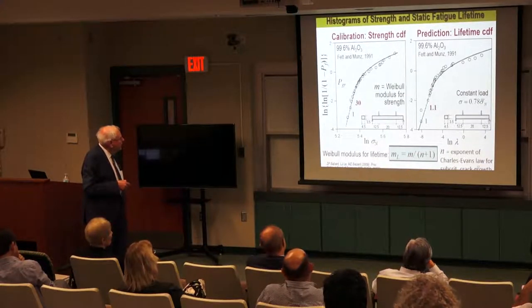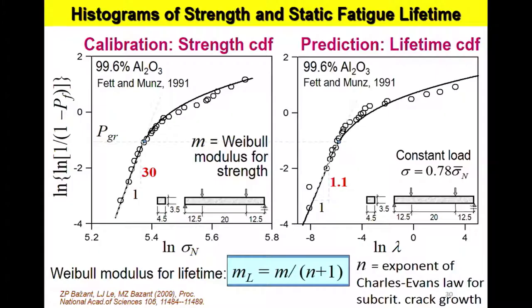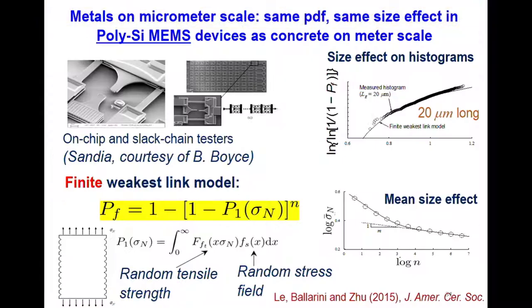There are not many tests, but Fett and Munz tested the same material, aluminum oxide. For short time strength, the slope is 1 over 30, so a very small size effect. So 30 to 1, very small size effect. Here the size effect would be 1 over 1.1, extremely large. Both are fitted with the same law, and this is verified by this analysis.